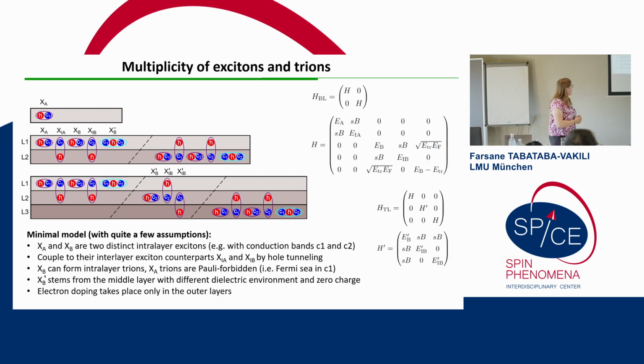So let me tell you about this model. We believe that XA and XB are two distinct intralayer exciton species formed with these two conduction bands, XA with the lower energy C1 conduction band and XB with the higher energy C2 conduction band. And then, as we apply a magnetic field, XA and XB couple to their interlayer exciton counterparts via hole tunneling. This is described in our Hamiltonian in these blocks here, where SB is the coupling term with magnetic field.